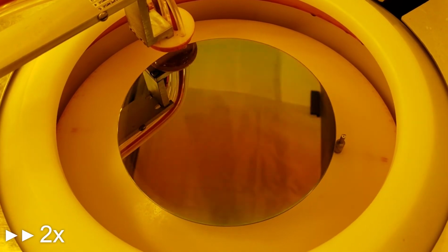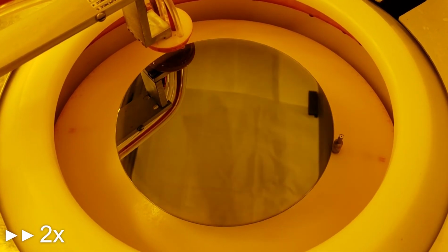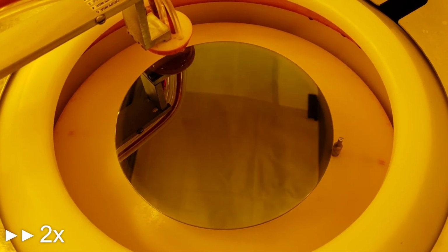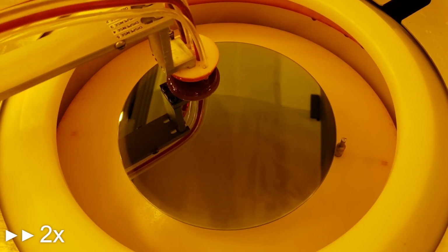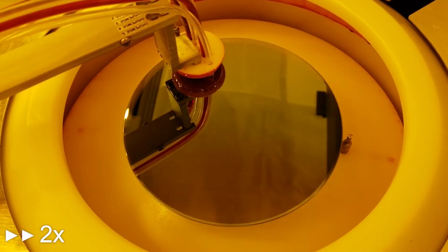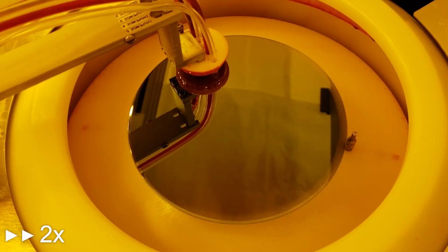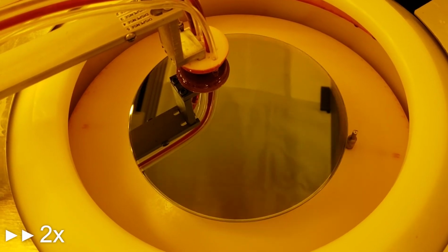Most of the solvent is driven out of the photoresist during the spin step, which turns the photoresist from a liquid to a solid. Next, the nozzle moves back over the wafer to remove the edge bead that forms during the coat process. The nozzle dispenses a thin stream of solvent just along the edge of the wafer to remove the photoresist that has built up there. Lastly, the wafer is spun dry.